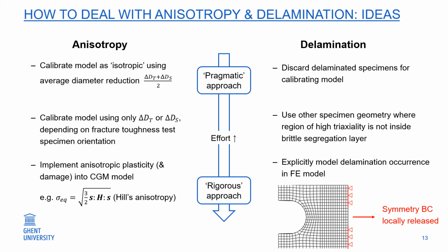Some ideas for taking these two into account are listed here. I ordered the approaches going from pragmatic, requiring little effort, to more rigorous approaches, requiring more effort to implement. For anisotropy, we could calibrate the model as isotropic, with the average diameter as input. Another option is to evaluate the crack growth direction for the fracture toughness test and calibrate the model using the corresponding orientation.